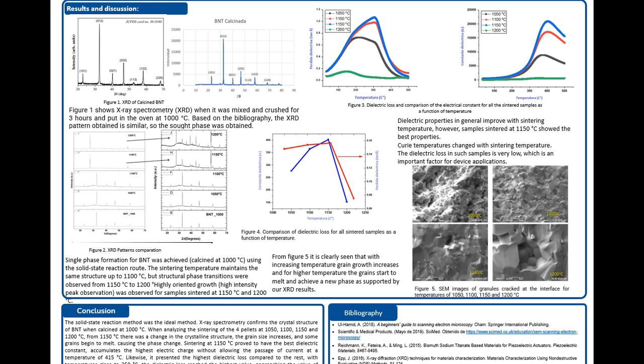This happened when we calcinated at 1000 degrees using the solid state reaction route. The sintering temperature maintains the same structure up to 1100, but structural phase transitions were observed from 1150 to 1200. Highly oriented grain, this is the high intensity peak as we can see in figure number 2, was observed for samples sintered at 1150 and 1200.